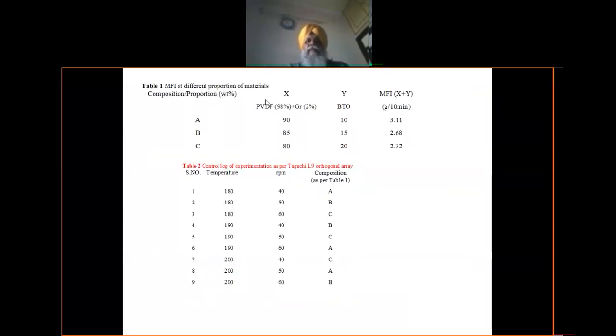So PVDF with graphene, as per the literature, more than 2% graphene reinforcement was not recommended. So different proportions of PVDF and barium titanate were selected. Their MFI was calculated. Now, one question you may have is, why am I interested in this MFI? You see, the commercial open source printers run with an MFI of around 2.5 gram per 10 minutes, right? If you select the proportion of the material in such a way that your MFI remains in that range, then you can print any material without any change in the hardware or the software of the system, right?